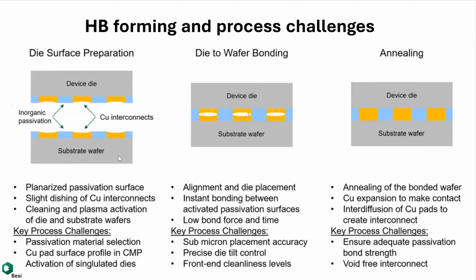But that's intentional, because this way they have a better chance of good alignment. The alignment is better than if the copper protrudes out. Imagine you have a protruding manner that connects to each other. Then the protrusion will squeeze and become bigger, right? And making it bigger is not good. You will lose the mechanical tolerance, and you will reduce the scaling.